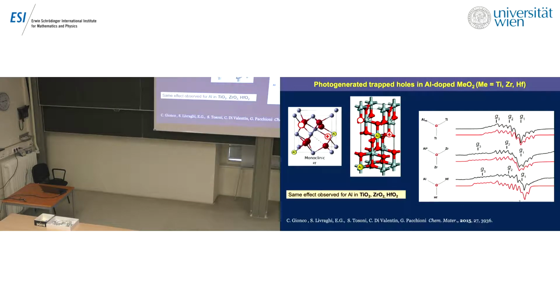We have this beautiful series of spectra obtained with aluminium-doped titania, zirconia, and hafnia. And in all cases, the g is different because there are different nuclei in the system, but you have always this series of six lines that allows you to measure the interaction, not, unfortunately, on the oxygen side, because it is oxygen 16 and not 17, but on the nearby aluminium. And this is a very tiny, tiny interaction that means that, once again, we have a strong localization of the hole on such an oxygen ion.